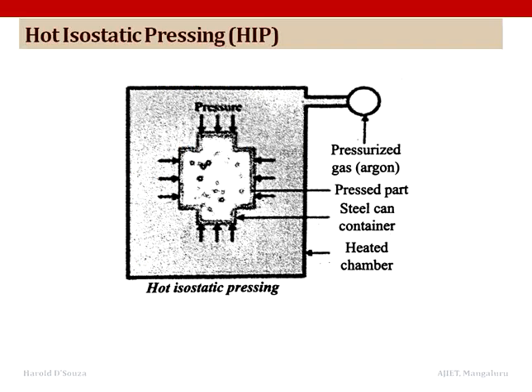Hot isostatic pressing. Hot isostatic pressing is a compacting process where high temperature and pressure are applied simultaneously in 3 dimensions to produce a dense component. The pressure is uniform in all the directions, so isostatic. Now at higher temperatures, the heated container deforms plastically and the powder is compacted within it under pressure. So no further sintering process is needed, as the combination of the heat and pressure during the process does it.